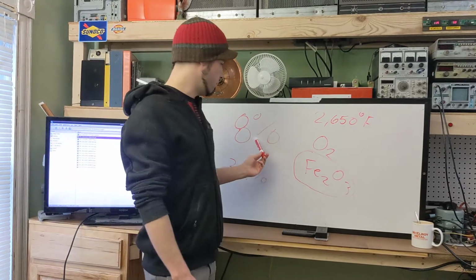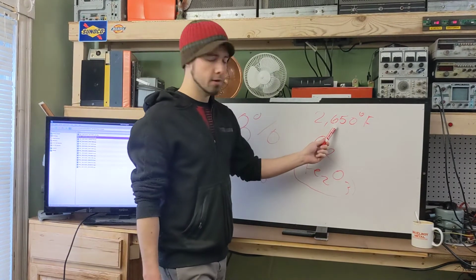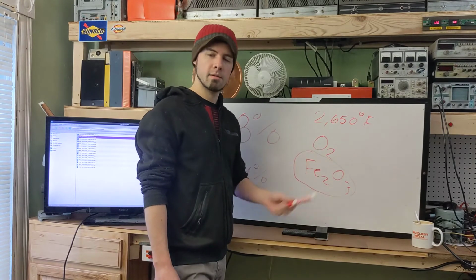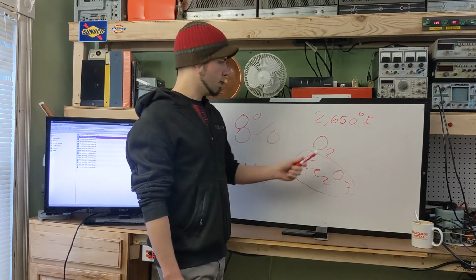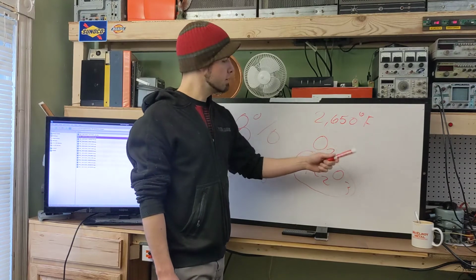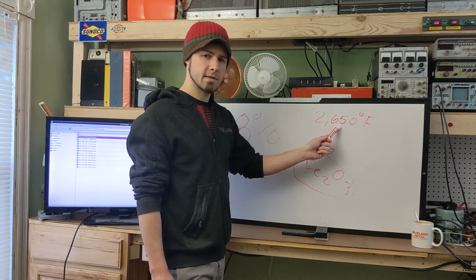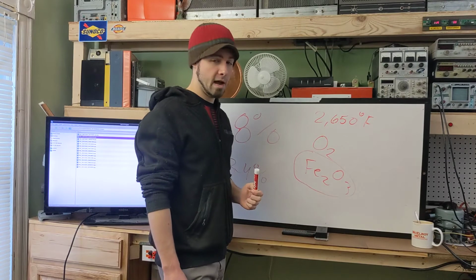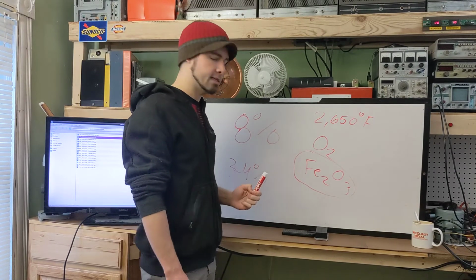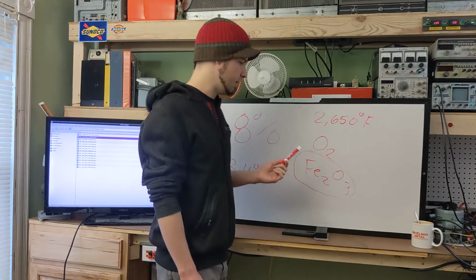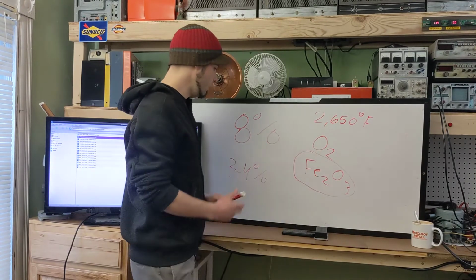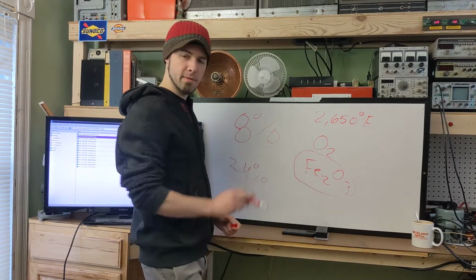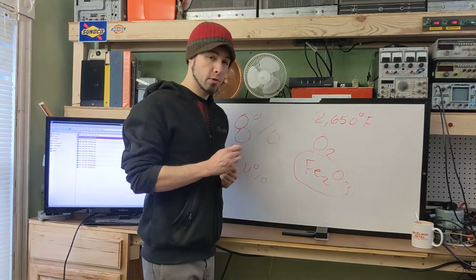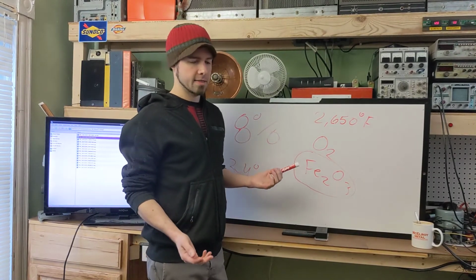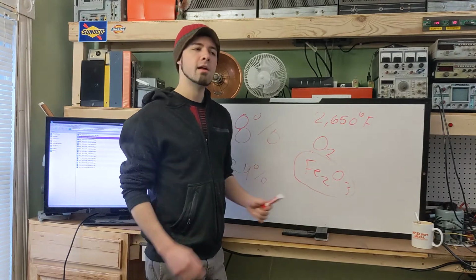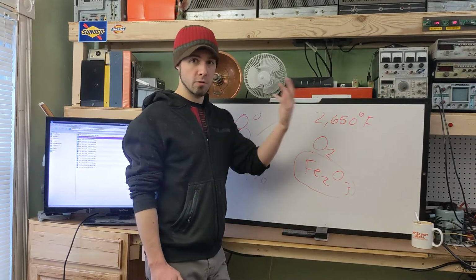Maybe someday in the future we'll be able to achieve these temperatures using electricity instead of burning fuel. So if we could electrically fire the cement kilns and achieve this temperature without fuel, that eliminates at least 40 to 50% of the CO2. And then the other side of it, the other half of the emissions, you may be able to capture that carbon dioxide gas. If you were to use electricity, then you can make the entire cement kiln a closed process.